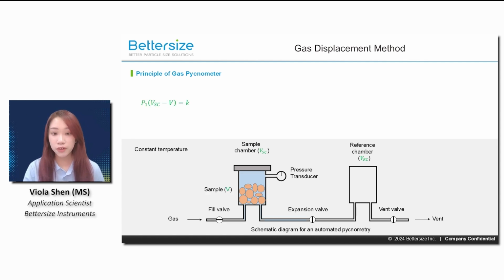So imagine we are now using a gas pycnometer. We start the measurement by opening the lid and placing the sample in the sample chamber. And then we close the lid, keeping the expansion valve closed. And we open the fill valve to allow a specific amount of gas to enter the sample chamber, then close the fill valve. The pressure at this point is recorded as P1, and we have a formula here.